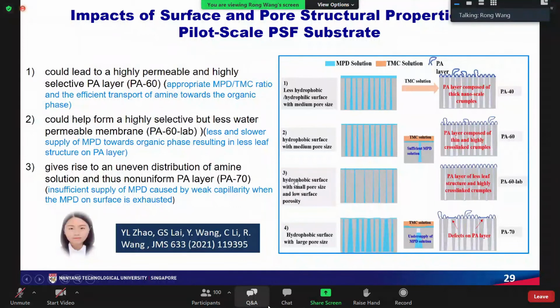We try to understand the impact of the substrate on the IP layer formation. We conduct a fundamental study. For example, we found the appropriate MPD/TMC ratio and the efficient transport of the amines toward the organic phase is critical. It could lead to a highly permeable and highly selective polymer layer, a polyamide selective layer.